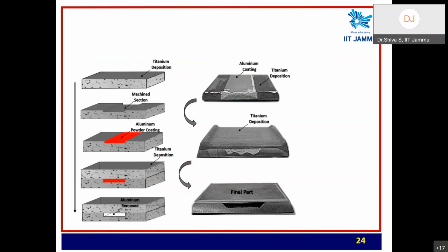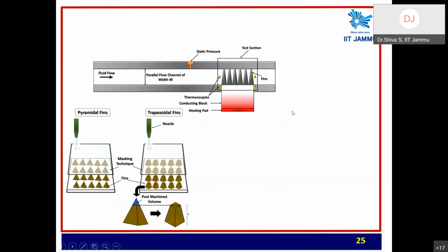Now you can see the various tracks, like you have a titanium deposition on aluminum, because joining titanium and aluminum in manufacturing is one of the most tedious tasks due to their respective nature. But what happens here, when you cold spray them, the sandwiching happens very, very easily, and the alloying also happens much more easily when they are previously cold sprayed and the shape has been maintained throughout. So this is also a much more efficient way of fabricating and creating dissimilar joints among the samples being fabricated.